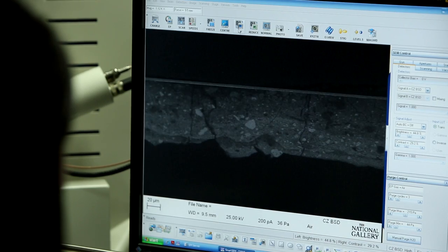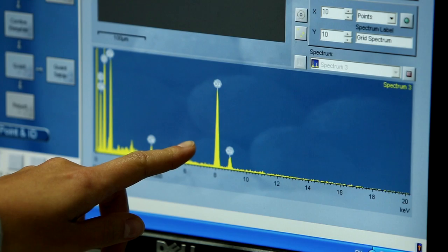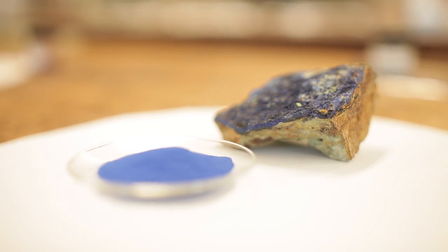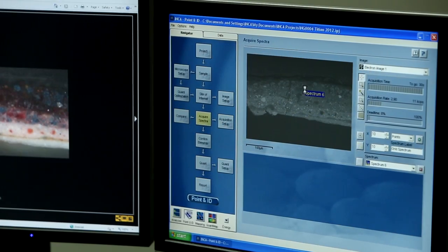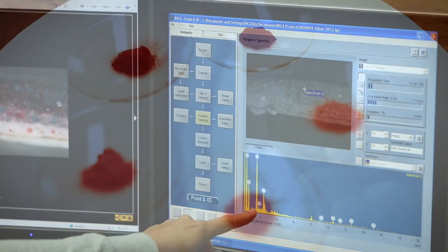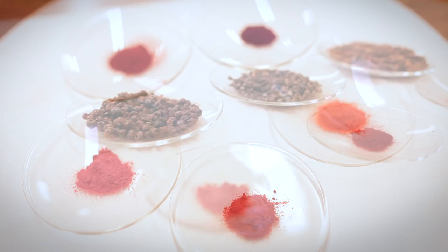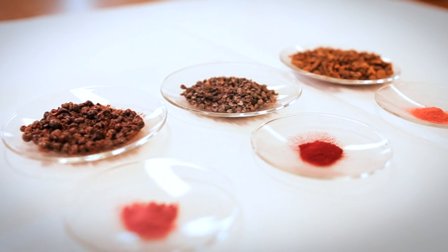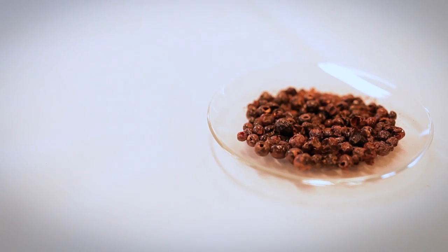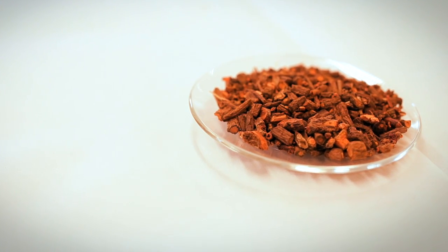The blue pigment in this purple paint contains copper, identifying it as the mineral azurite. The red pigment contains aluminium, which is characteristic of what are known as red lake pigments. The colour in red lake comes from the dyestuff in insects, such as kermes or cochineal, or plants such as madder root.